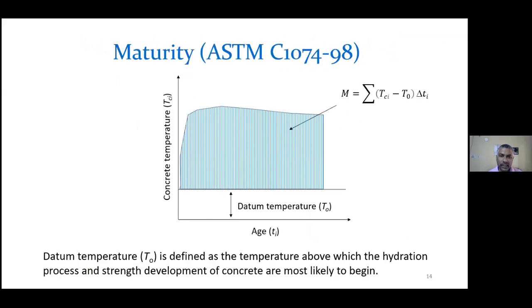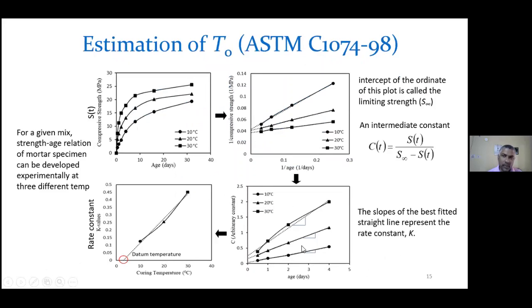And now see how to find out this datum temperature. This datum temperature comes only for the American standard, and the code gives you some procedure to calculate it. Otherwise, you can take some values conservatively. The code says some values, but it is not very difficult to develop this value of datum temperature. As per this code, for a given mix of concrete, we take the strength-age relation of a mortar specimen. Only the mortar specimen: whatever the cement to aggregate ratio, a similar cement to sand mortar we have to prepare. For the given mix, represented by cement to aggregate and water to cement ratio, keeping everything intact, we can develop the mortar specimen of a particular mix.